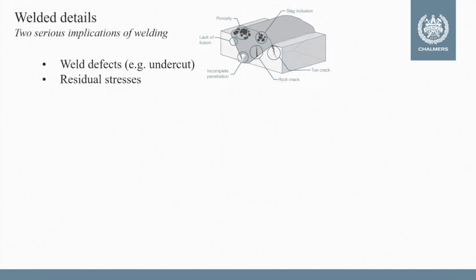And starting just in a general sense, looking at welding and how welding influences the fatigue performance of welded details, which we find in all modern bridges today, there are in particular two aspects that are very important to consider and that have serious implications on the performance of welded details with reference to fatigue. The first one is the presence of weld imperfections or weld defects of different types: undercuts, porosity, lack of fusion, and so on. And these will in principle be very serious local stress raisers. They will behave like small micro cracks. That makes the fatigue life of welded details in principle mainly crack propagation, as we have defects that more or less are small micro cracks.